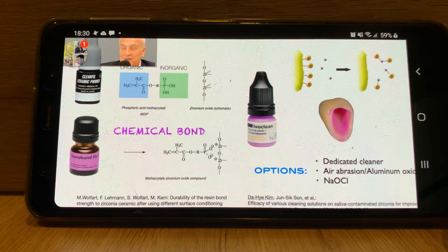especially if you want to enhance the time element, because it's going to be a long bonding process. So what I do is I use some sort of chemical means as a kind of insurance policy. There are two things you can use. One is, in the literature, it says that you can use sodium hypochlorite. If you're thinking about alcohol or acetone, they actually will not remove the phosphates from that surface. Sodium hypochlorite probably will, or you can use a dedicated cleaner from a manufacturer. Ivoclean happens to be one of them. There's something called Zircleaner. There are lots of products on the market. You could choose one of them.